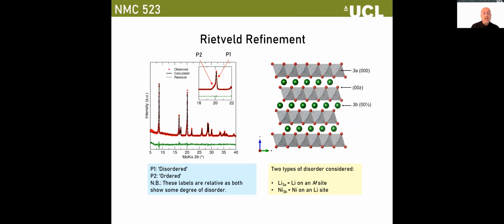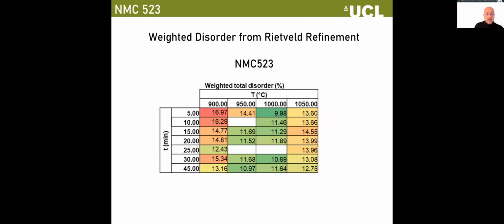And what Tom was finding in particular when he was looking at some of the Rietveld refinement, and this is on the NMC523 material, was that in the initial few minutes, as you're heating up these materials, often you'll see what looks like some very disordered structures, maybe more than one disordered phase, which are distinctly different enough that you can separate them in the XRD data. But as that develops, you essentially just see one single disordered phase. And what Tom has been trying to do is weight the total amount of defects by these contributing phases or the single phase, and plot that. And we've been measuring the capacity of these batteries in the normal way. So this is a map of the weighted disorder.